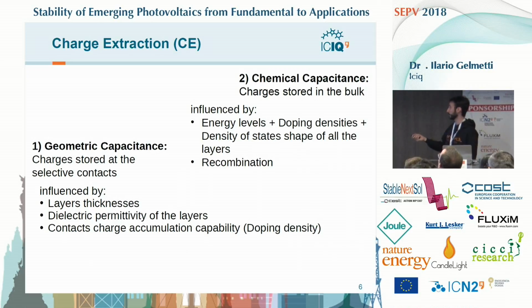Okay, so from the geometrical capacitance, the information that we can take out is basically the layer thicknesses and the dielectric permittivity of the layers, which is just the parallel plate capacitor physics, and the selective contacts charge accumulation capability, which mainly depends on the doping density. From the exponential part, the chemical capacitance, we can have information on the position of the energy levels, the doping density, and the density of states of the layers, and it can be affected by the recombination.